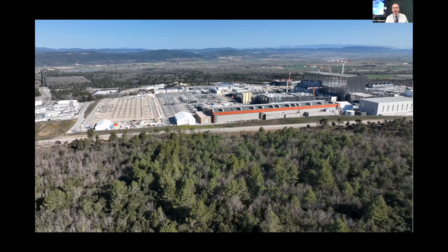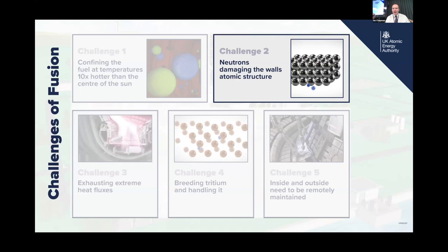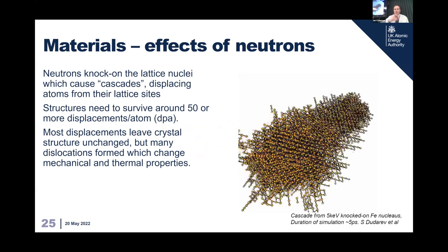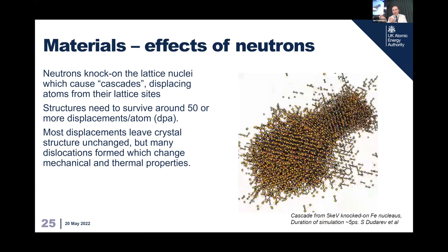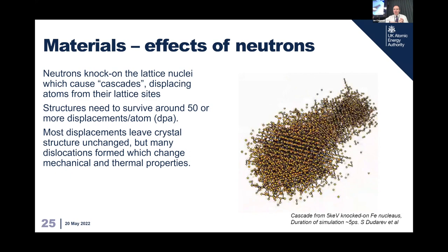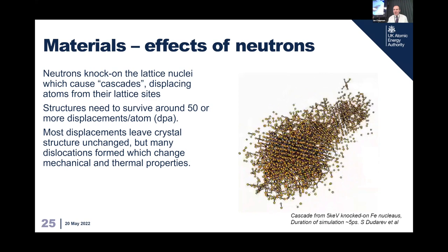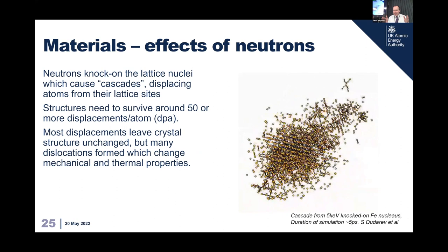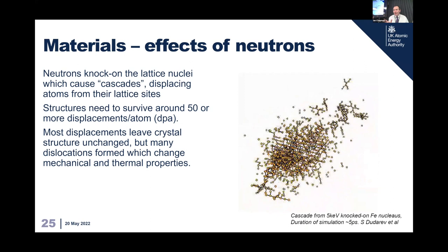The second challenge that we talked about was how the very high flux, very high energy neutrons affect the wall. Now, each one of those neutrons will cause a displacement. That in and of itself is not a problem, but those displacements can cause knock-ons and can cause what we call sort of cascades or dislocations through the material. And as those dislocations propagate, they will lead to swelling, they will lead to cracking for sure. And that really affects the lifetime of the plant. And now if the armor on the front lasts for 5 years, that's probably fine. But if it lasts for 5 months, it's probably not fine.